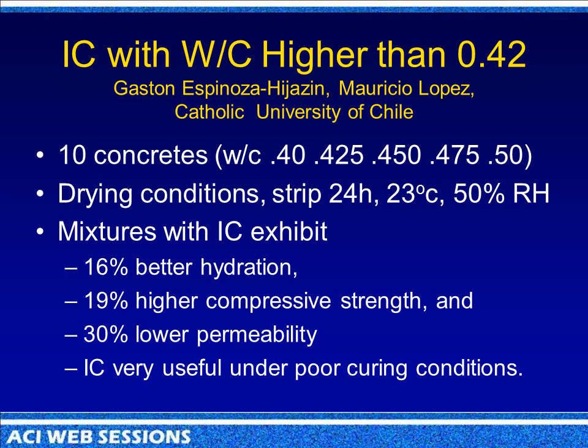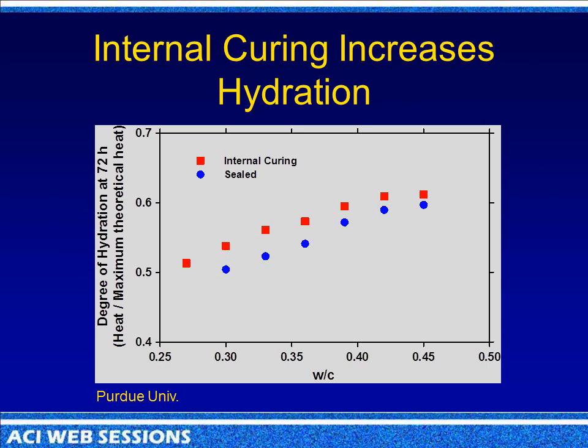Now, this is pretty impressive. 16% increase better hydration, 19% higher compressive strength, 30% lower permeability, and internal curing was very useful for poorly cured concrete. Now, where can you get poorly cured concrete very quickly? On pavements, on surfaces, a lot of evaporation. Purdue came up with the same thing. Look at their water cement ratios went up here. The internal curing one definitely had better hydration than the one without internal curing. So it's not just coming from one source.